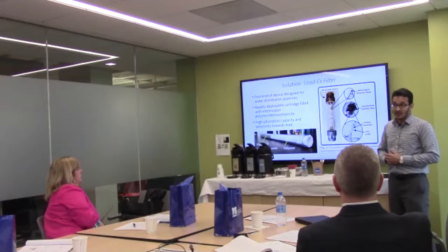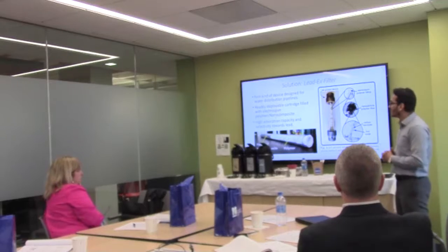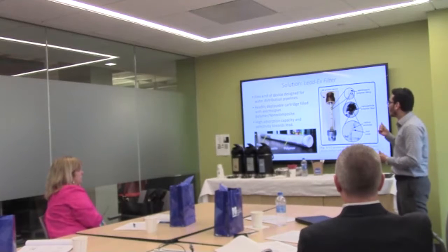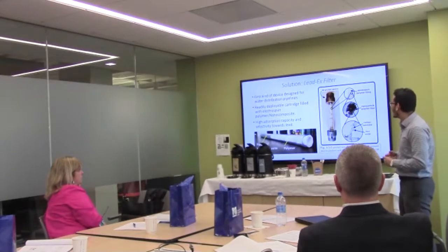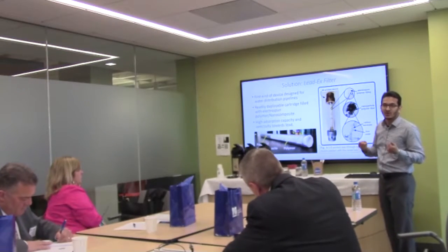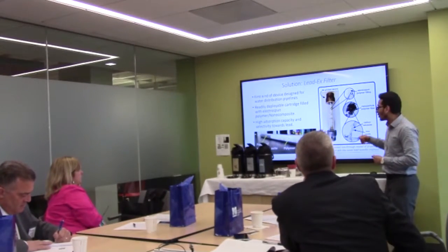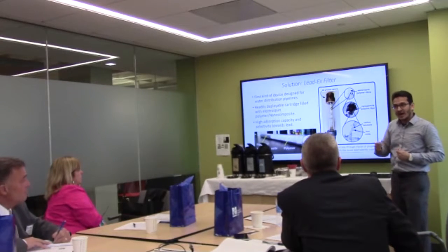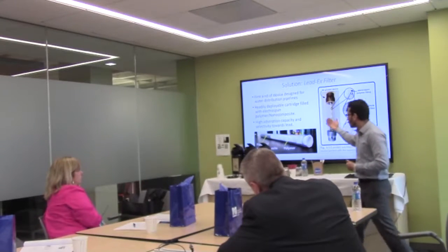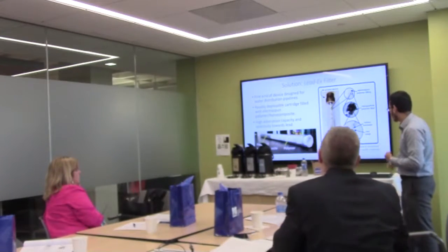So what's the solution? The LeadEx filter is a solution, the first kind of device designed for water distribution pipelines. It's readily deployable, it can be immediately deployed in the form of a cartridge, which is prepared from an electrospun polymer nanocomposite. Basically we have two ingredients: electrospun polymer fibers prepared by electrospinning, a very common process, which is scalable as well, embedded with carbon nanotubes and iron oxide nanoparticles. Once they are embedded, they have a higher selectivity towards lead and can absorb lead. Just to show you the difference between the polymer and the polymer nanocomposite, the difference is shown with the gray color and the white color.